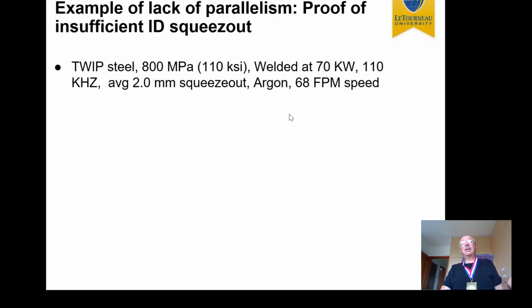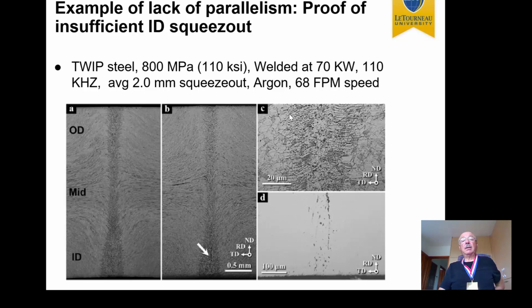For instance, if you look at the lack of parallelism of an insufficient ID squeeze out, here's an example of a TWIP steel from the literature, 800 megapascal strength, welded at 110 kilohertz, which is low in my opinion. And look at what happened. They clearly showed inclusions in an unetched sample at the ID side of the pipe. And notice what happens. Right there, the parallelism changes. So the material becomes trapezoidal, which means that it did not squeeze out properly.